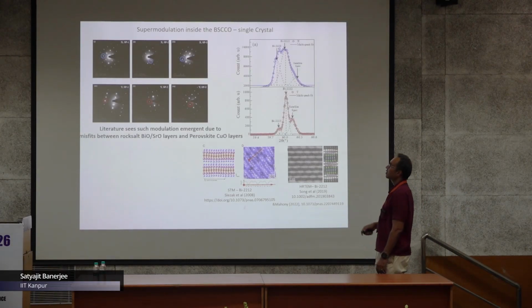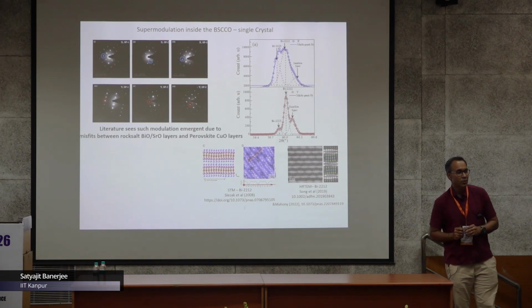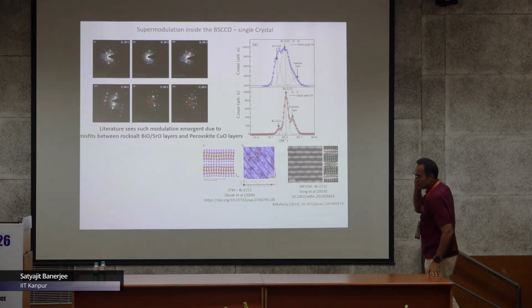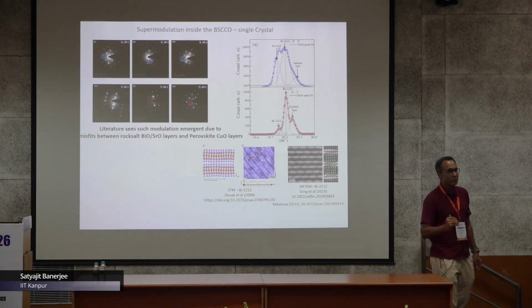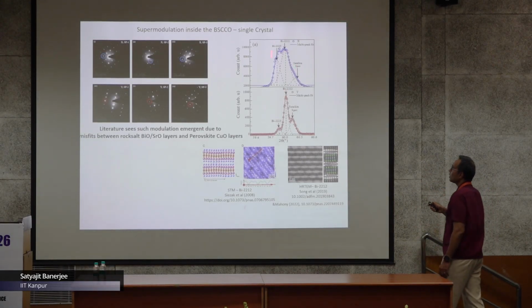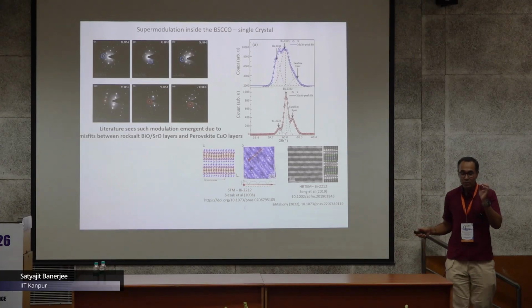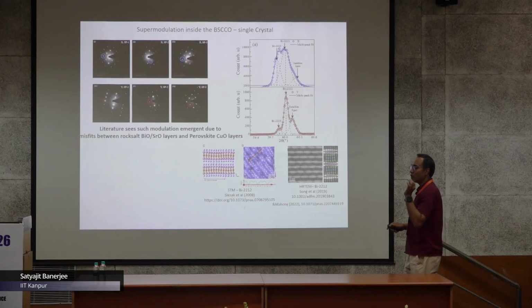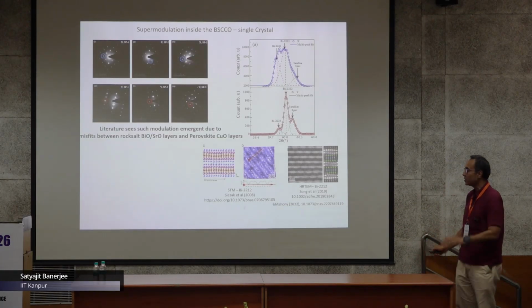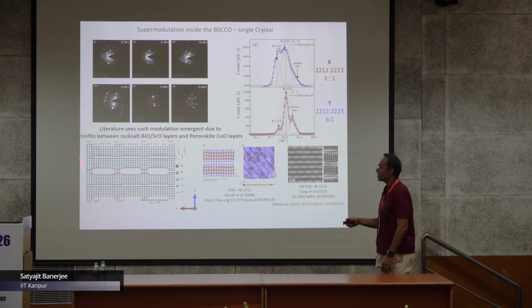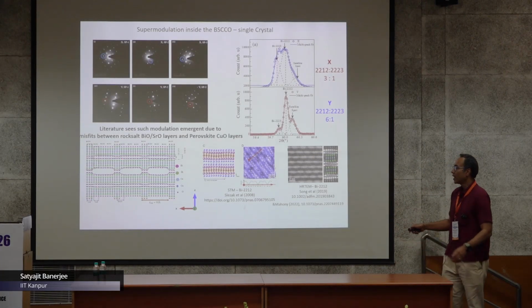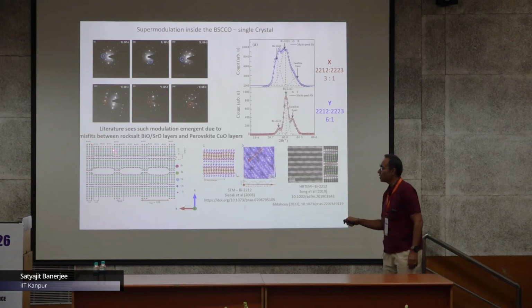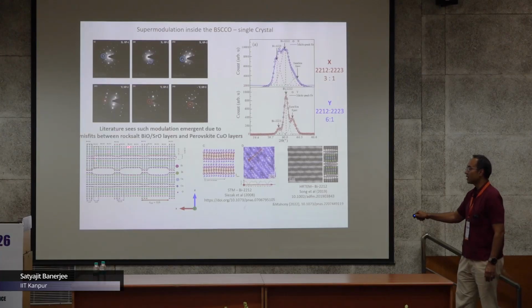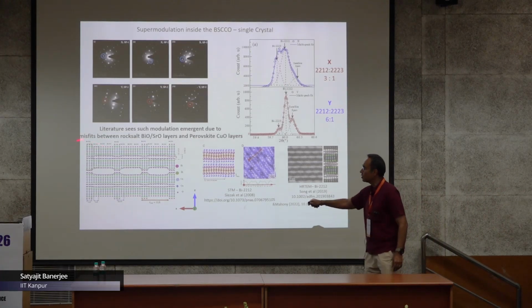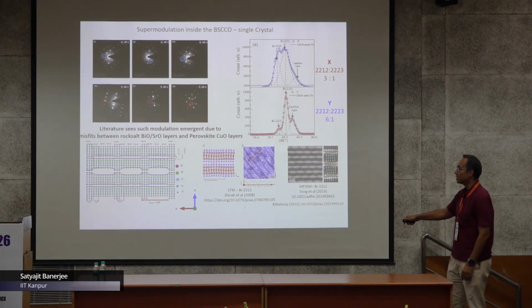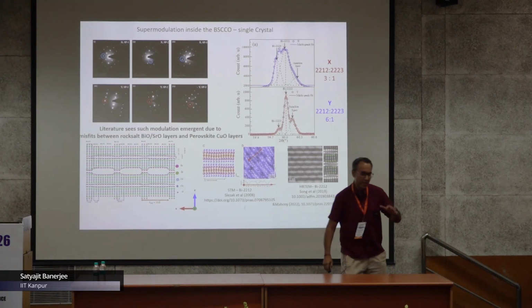Now, in the 2223 phase diagram, whenever you try to grow 2223, a little bit of 2212 always tries to grow too, since 2212 is the most stable phase, entering the system in roughly a 3:1 ratio. If you do a simple structural analysis and take one unit cell of 2223 and 3 unit cells of 2212, you can see that because the heights of the cells are not equal, a modulation emerges, and the order of this modulation is around 28 nanometers or so.